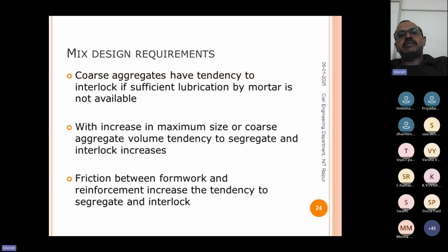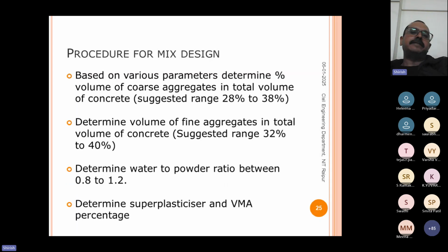With increase in maximum size or coarse aggregate volume, tendency to segregate and interlock increases. Friction between formwork and reinforcement increases the tendency to segregate. Now, if you remember that photograph which I have shown, the reinforcement was so high that only mortar may cross that. So what is possible? In such case, we can design a self-compacting concrete with only 10 mm maximum size of aggregate. Such things are possible and such corrections should be made.